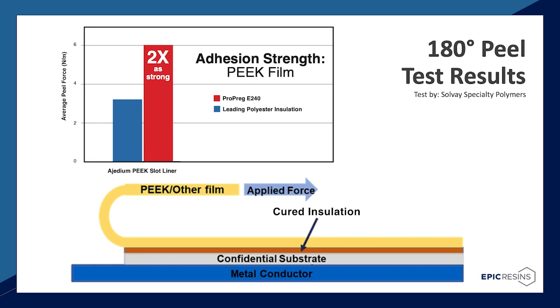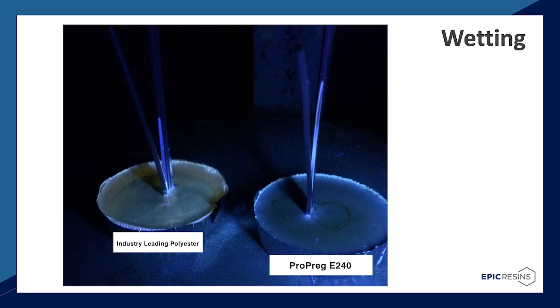to the leading polyester. This adhesion improvement is due to the molecular functionality and its ability to wet the surface of PEEK. This wetting is illustrated in the image shown here. ProPreg E240 passively climbs up the PEEK-coated wire at a rate significantly higher than that of the polyester.